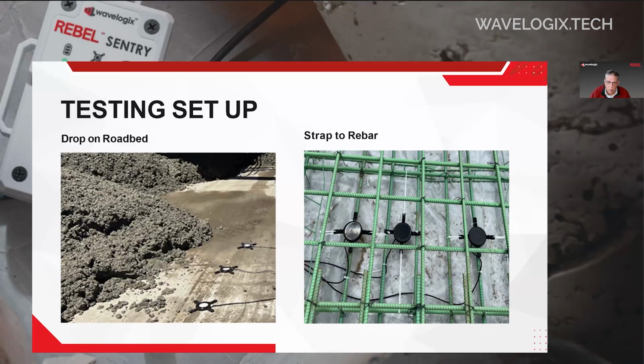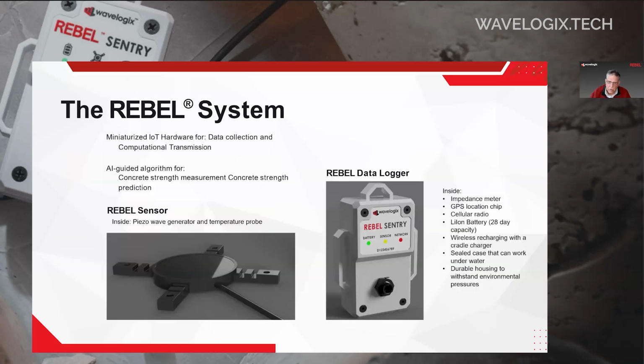The sensors are very easy to deploy. You can either put them on the ground if you're doing pavement and roll the concrete over it, or you can tie it to rebar. So it's simple to deploy. Cable comes out from the sensor, and that plugs into a data logger. So the sensor itself is relatively flat, half an inch thick, about 4 inches in diameter. It has a piezo wave generator in it, and we throw a temperature probe in. So we're measuring both the temperature of the concrete and the strength, and looking for the resonant frequency.